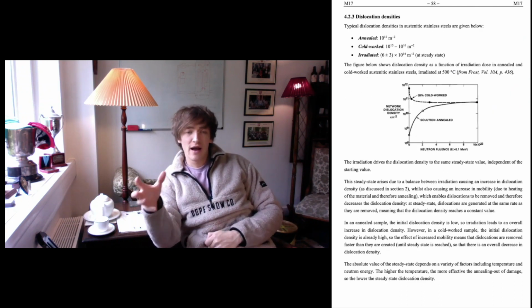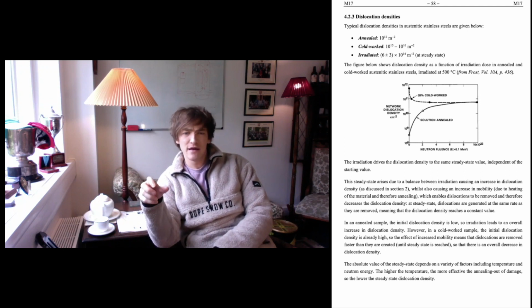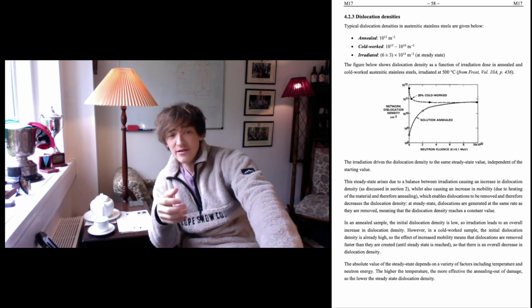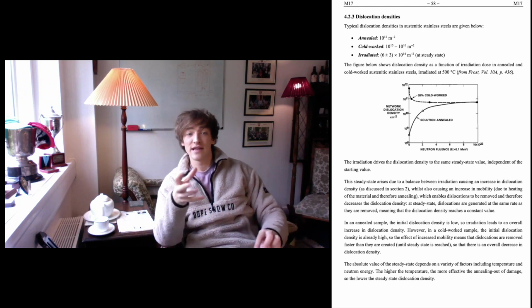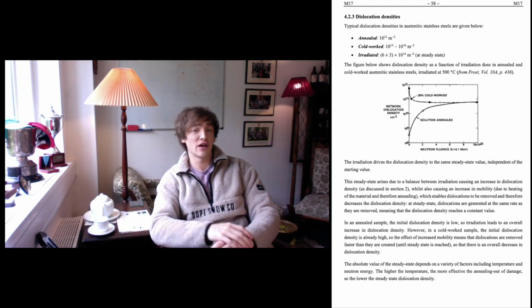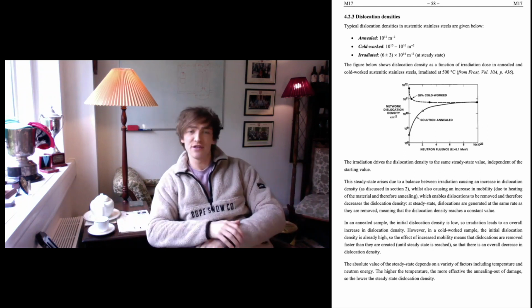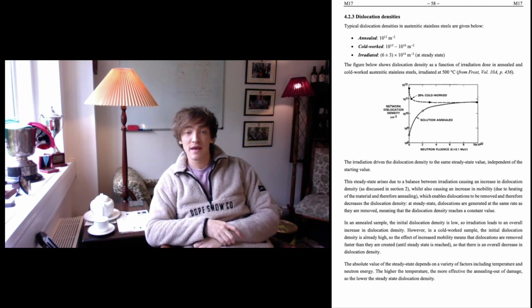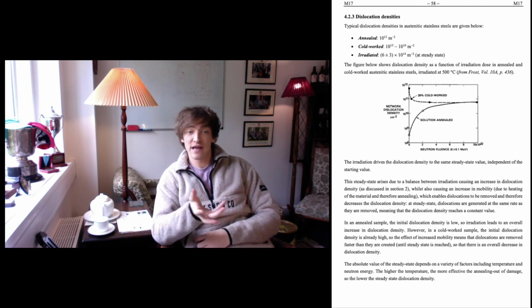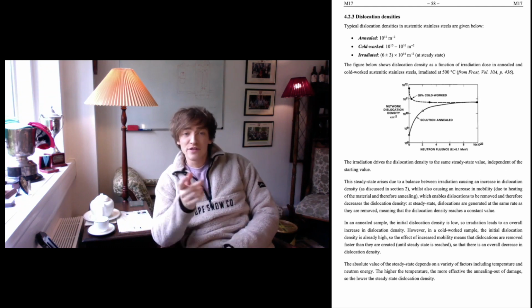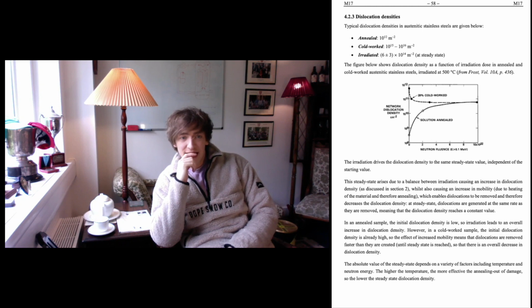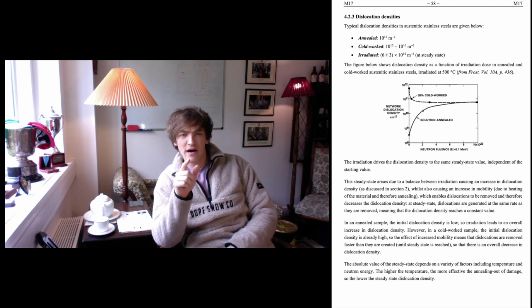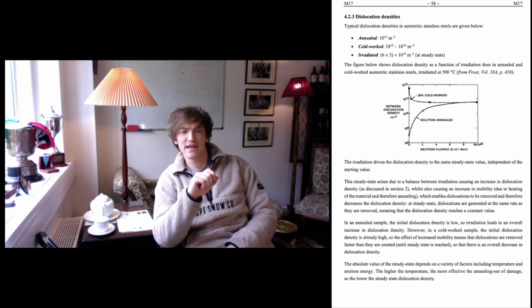So I've mentioned before how dislocations can be produced during irradiation, but it's a little bit more complex than that. Depending on irradiation conditions, an alloy will show an equilibrium dislocation density that is eventually reached under irradiation. You get this equilibrium dislocation density regardless of what condition you initially put the alloy into to be irradiated, be it higher or lower than the original dislocation density, basically. And that's what you see in the figure on page 58. If you look at that figure, you can see that at a relatively high dose, both cold worked and solution annealed stainless steel will reach the same dislocation density after irradiation.